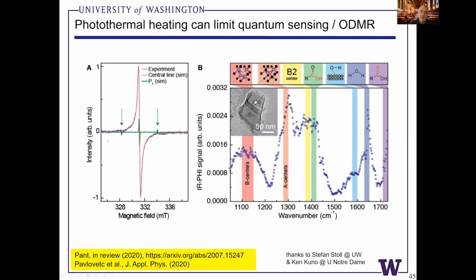We did some EPR measurements on these samples. They have around 40 ppm substitutional nitrogen. So these are fitted, very faint P1 center peaks. And then there are also some paramagnetic surface states just from the milling and processing that we use.